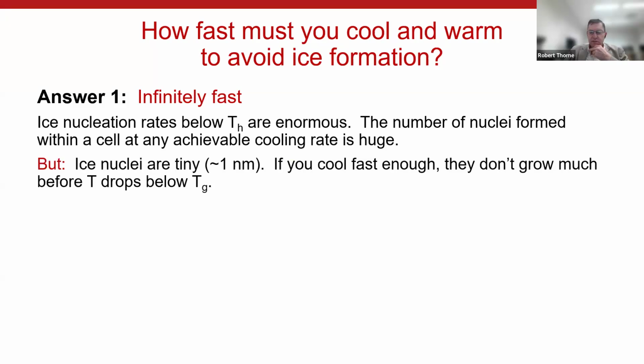But fortunately, ice nuclei are really tiny. They have about 100 water molecules in them. They're about a nanometer in size. So it's okay if they form as long as you don't give them a chance to grow. And we'll see in a moment that their growth rate drops as temperature drops.